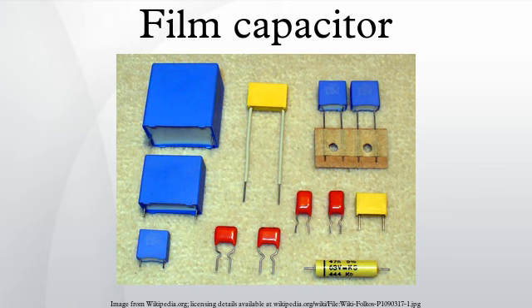For similar reasons, film capacitors are widely used as decoupling capacitors to suppress noise or transients. Film capacitors made with lower-cost plastics are used for non-critical applications which do not require ultra-stable characteristics over a wide temperature range, such as for smoothing or AC signal coupling. Polyester film capacitors of the stacked type are often used now instead of polystyrene capacitors, which have become less available. Metallized film capacitors have self-healing properties, and small imperfections do not lead to the destruction of the component, which makes these capacitors suitable for RFI/EMI suppression capacitors with fault protection against electrical shock and flame propagation, although repeated corona discharges which self-heal can lead to significant loss of capacitance.